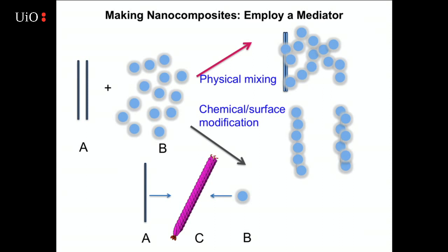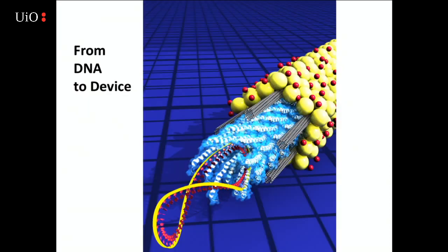You can think about physical mixing or chemical modifications to the surface. But in this case, you may not get very homogeneous mixing. In this case, you might actually affect the surface in a deleterious way. And so we use this virus as a mediator to have one gene that picks up the carbon nanotube, another gene that grows titanium nanoparticles. And so we spent the last several years in my lab thinking about how do you go from a DNA sequence to a functioning device.